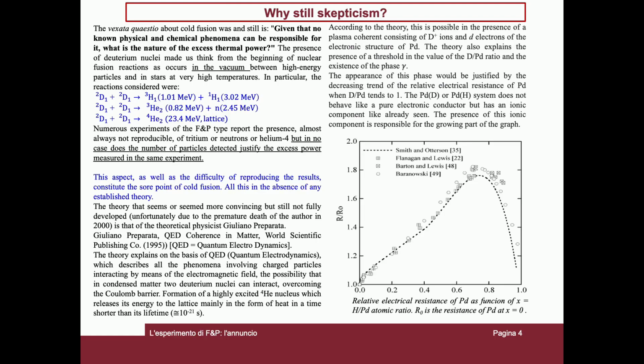The theory that seems or seemed more convincing, but still not fully developed, unfortunately due to the premature death of the author in 2000, is that of the theoretical physicist Giuliano Preparata. The theory explains, on the basis of quantum electrodynamics, which describes all the phenomena involving charged particles interacting by means of the electromagnetic field, the possibility that in condensed matter two deuterium nuclei can interact by overcoming the Coulomb barrier. Formation of a highly excited helium-4 nucleus, which releases its energy to the lattice mainly in the form of heat, in a time less than its lifetime, which is about 10 to the minus 21 seconds.